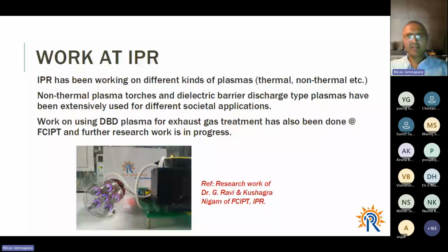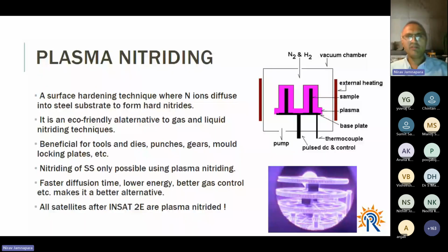So plasma assisted manufacturing, plasma nitriding is one such process wherein we use nitrogen and hydrogen mixtures. We don't use ammonia. Nitrogen-hydrogen mixtures can be used to tailor specific surface chemistry, thereby achieving very specific tailored process properties which are otherwise not possible to achieve.